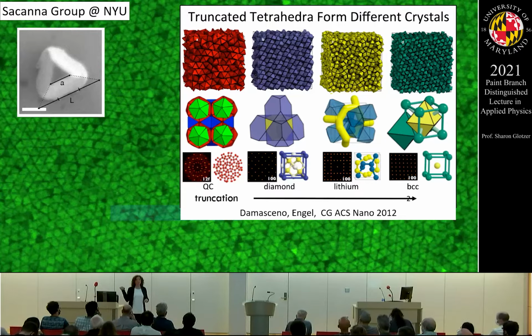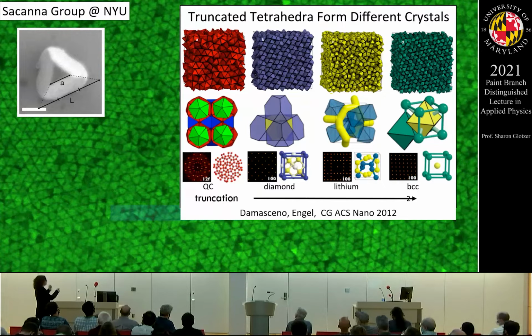At this larger scale of microns, where you use plastic to get your particles, like polystyrene or PMMA, or you could also use silica, then it's possible to screen out all the interactions, but it's really hard to make shapes that aren't spheres or ellipsoids. So this was actually a big achievement for his group, to make these truncated tetrahedra. And here is an image from confocal microscopy showing that they self-assemble into this diamond structure that we had predicted in our simulations.